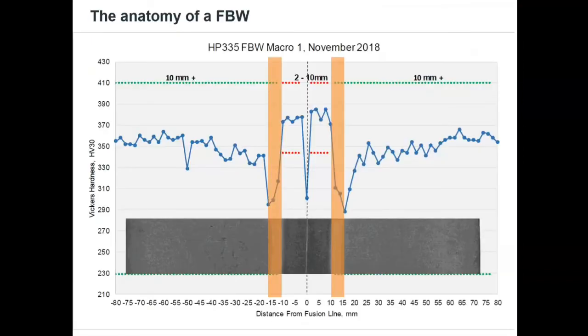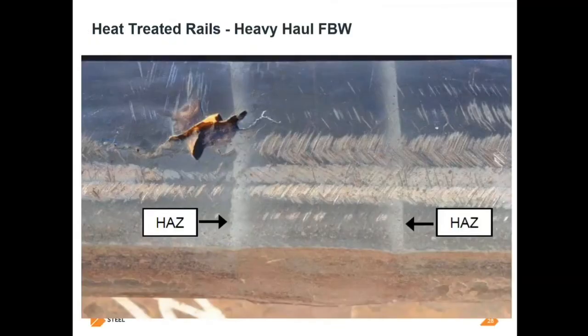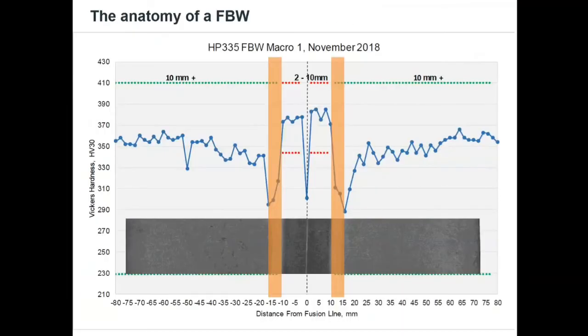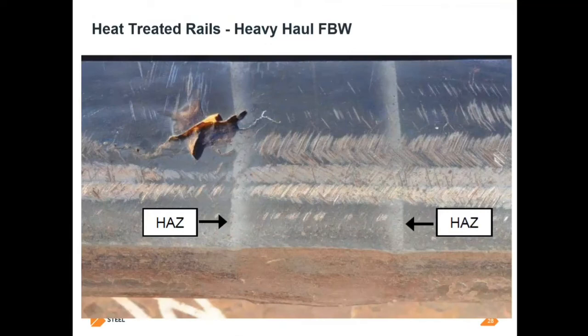Then we have the intercritical heat affected zone. That's this light gray region where you have a massive drop in the hardness. So what's happening here is that you're getting some spheroidization of your pearlite, and it's important to minimize the width of these zones because they're unavoidable. But the narrower they are, the more chance the contact patch of your wheel running along the rail has to just step over it. You have a hard critical heat affected zone and then the parent either side and you just bridge over it. So it's important to keep them narrow. If you don't keep them narrow, then you end up with defects like this.